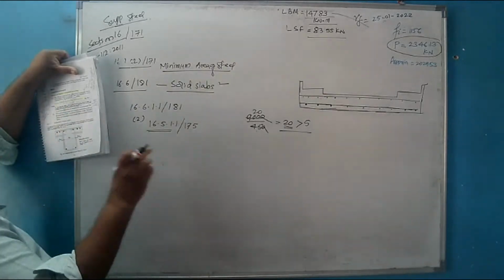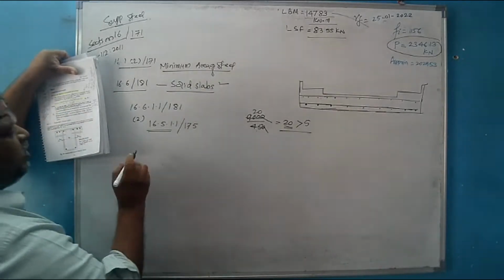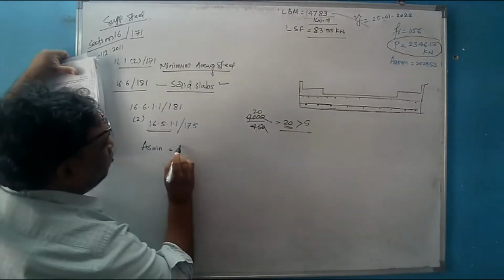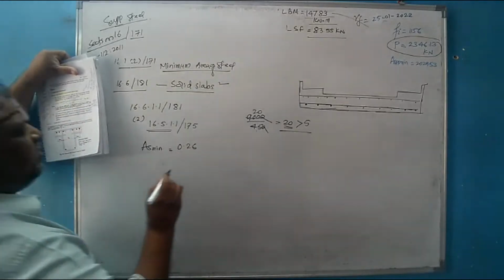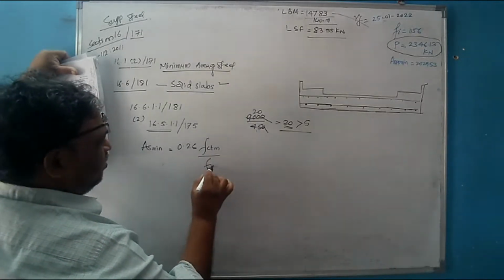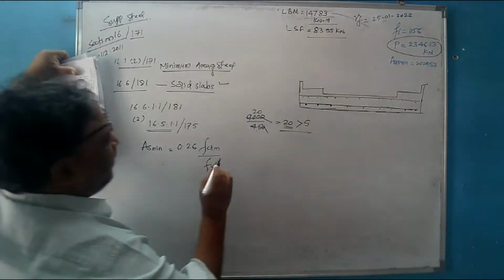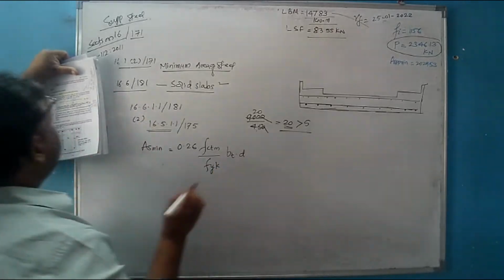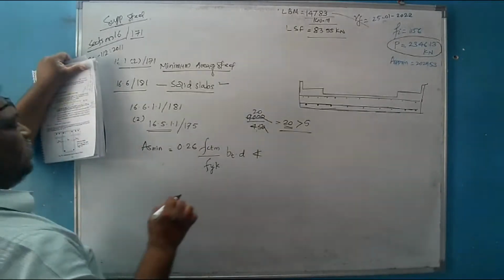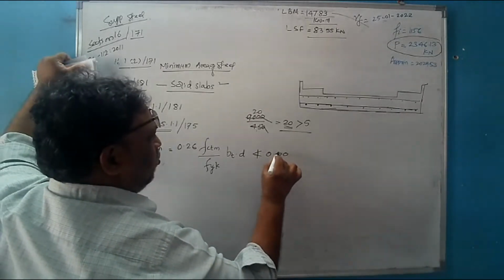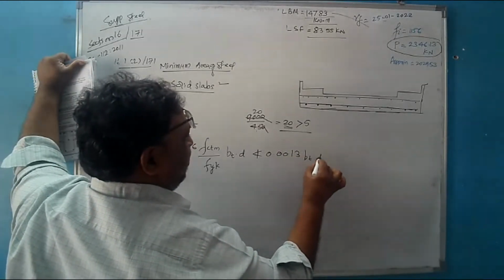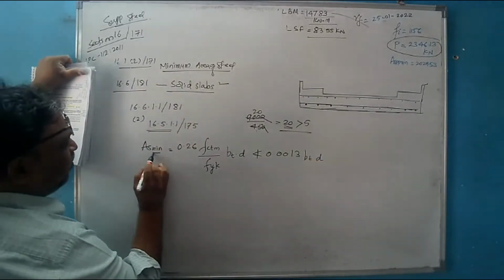अभी ये ductility criteria. This is from the requirement of the ductility. What is it? As minimum. That is the minimum area of steel. Must be equal to 0.26 fctm divided by fyk, bt into d, but not less than, so it cannot be less than 0.0013 bt into d. This is for the minimum area of steel.